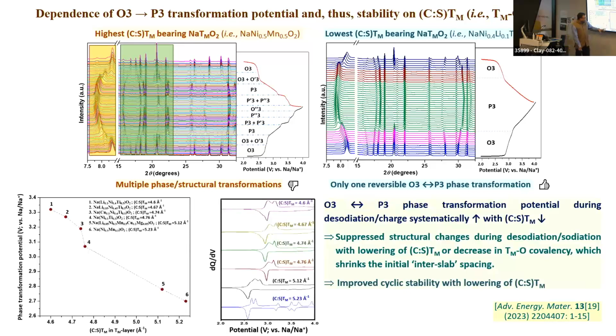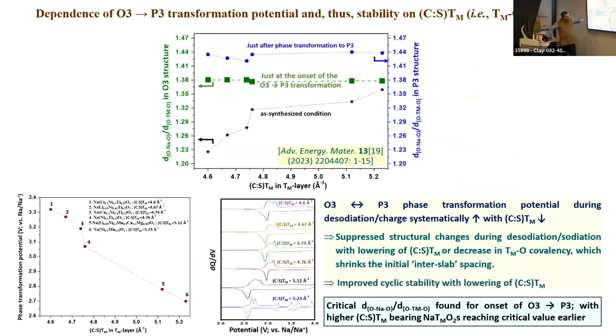So dQ/dV also shows that with the lower charge to size ratio, the potential for the first transformation moves to a higher value, to a higher potential, which means we can extract more sodium before it initiates the first structural transformation, as the charge to size ratio is lower. Now, from our in situ XRD, we figured out that there seems to be a kind of critical ratio between the interslab spacing to the slab thickness at which the O3 to P3 structural transformation gets initiated. So if the initial ratio is much lower, as with the low charge to size ratio containing material, then a lot more sodium can be pulled out before it hits this critical ratio and the structural transformation. Whereas pulling out a little bit of sodium from this will lead to initiation of the first transformation, and no wonder it will undergo all the transformations and it will get damaged very fast. Right? So yeah, that's what it is.